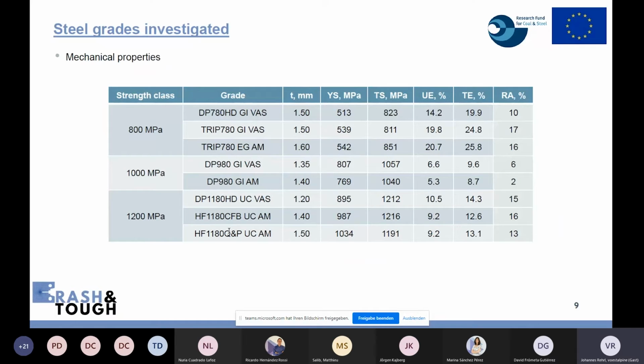So the two TRIP steels in the class of 800 megapascal had the highest content of retained austenite and showed the highest elongation values. The dual phase high ductility grade in the strength class 800 megapascal had a lower yield ratio, a lower yield strength when compared to the TRIP steels. In the 1000 megapascal class, we had one dual phase grade with about 6% of retained austenite and one grade with negligible content of retained austenite.